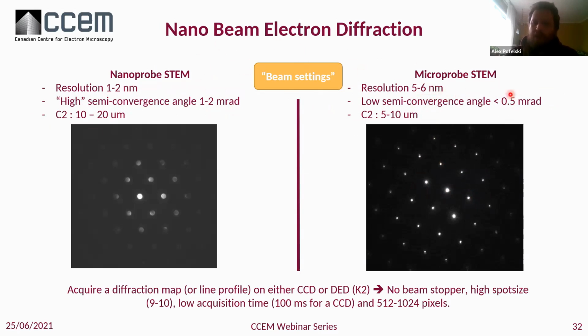As a consequence, we have two types of resolution. The microprobe will be poorly resolved, but will have a nice, well-defined, very small spot, while the nanoprobe will have better resolution, but a more spread beam. And then, whatever mode you are going with, you just have to acquire a diffraction map or line profile on either the CCD or a direct electron detector like the K2 that we have on the Titan 1. There's no need to have any beam stopper. Usually we go with a high spot size to reduce the intensity, and usually also a low acquisition time, so 100 milliseconds for CCD. And then depending on the level of sampling you want to use, usually 512 to 1024 pixels for each diffraction pattern.